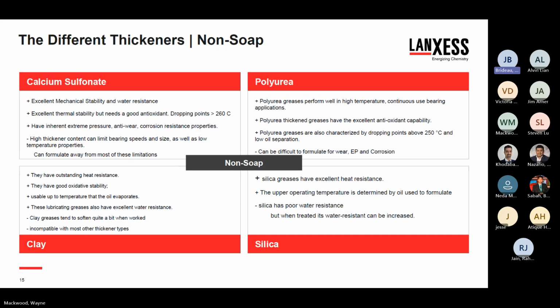And then finally, calcium sulfonate, all-round excellent products. They have all kinds of inherent properties like corrosion resistance, anti-wear, EP, excellent mechanical stability, very good thermal stability, but they definitely need antioxidant. Some of the highest dropping points in the business. The one issue with calcium sulfonate is that it tends to be a much higher thickener content, which can limit bearing speeds and the size of bearings that can be lubricated, as well as low temperatures. But quite honestly, given the right oil viscosity and some processing conditions, you can formulate away from a lot of those issues as needed.